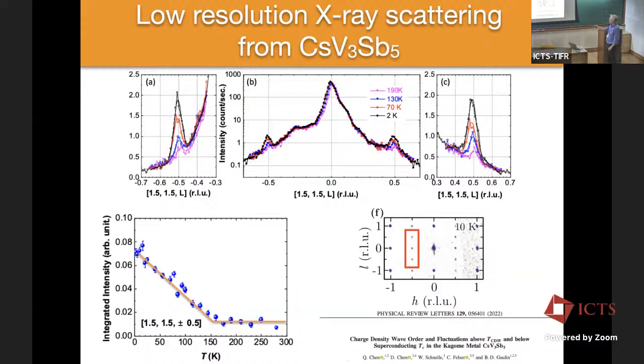And I'm showing you intensity on a log scale. So if you just look at the central feature here, this is intensity on a log scale as a function of a particular scan in reciprocal space. It's actually a scan along the L direction, which is the stacking direction. And I'm going to use one of these panels from data that I showed you earlier. So these actually are not the same data, but I just wanted to show you what this sort of scan looks like in reciprocal space.